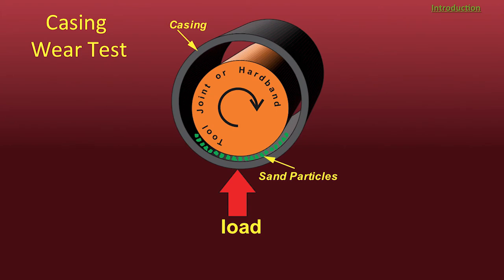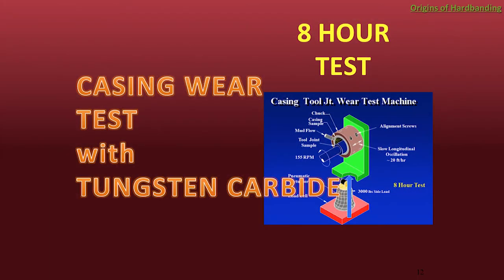Quite simply, a tool joint with hard banding is loaded into a fixture that houses the specified casing. The tool joint is then rotated at 155 RPM, while at the same time, a mud solution of 7% sand is continuously fed onto the rotating tool joint. A 3,000 pound load is also applied while the tool joint is rotating. The test runs for 8 hours and stops periodically to check the depth of wear in the casing and the tool joint. Valuable data, such as a casing wear number, or factor, torque, friction, and tool joint wear, just to name a few, are collected and reported.